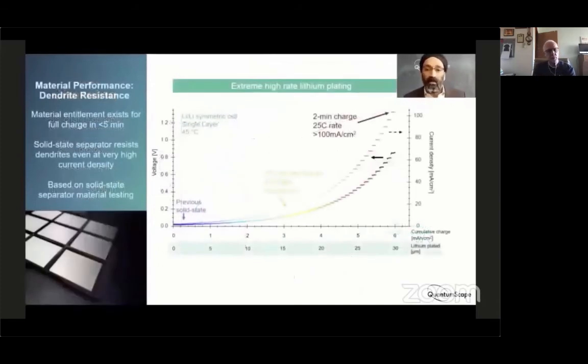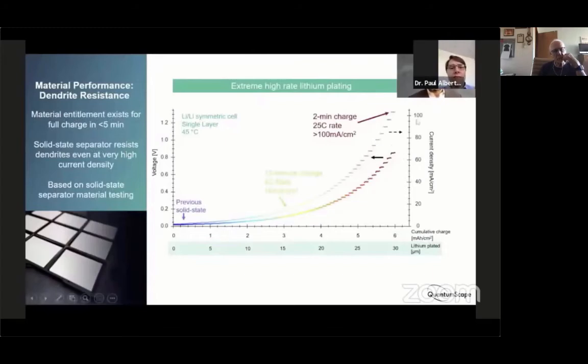Here's an even more exciting chart that the battery experts in the audience will be blown away by. This is a test that tries to look at how much current density the separator can handle without dendriting. And what you see is on the axis on the right, that's the current density. And by way of comparison, conventional solid-state efforts under these conditions really can't get much above a few, single-digit milliamps per centimeter squared before they fail. So they will fail at current densities around this level here.